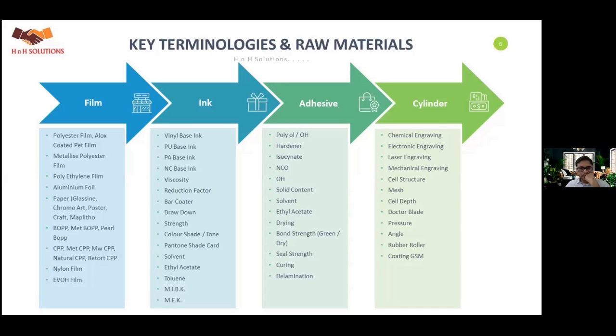Doctor blade is required to wipe off the excess ink or adhesive. Rubber roller is required to transfer ink or adhesive from cylinder to film. And doctor blade's pressure and angle is required to adjust the coating GSM.